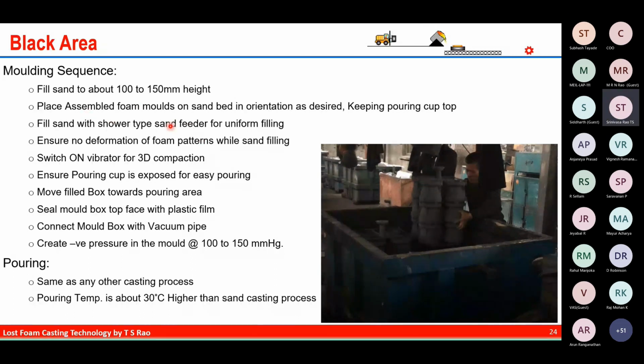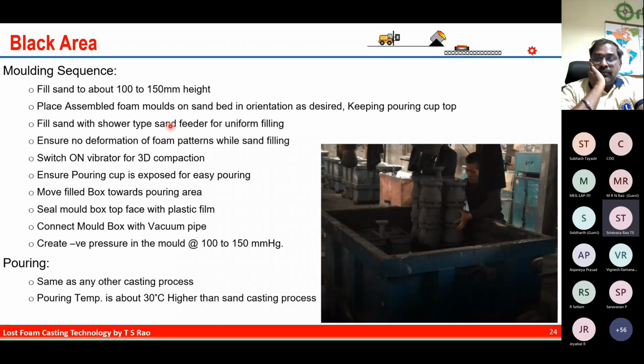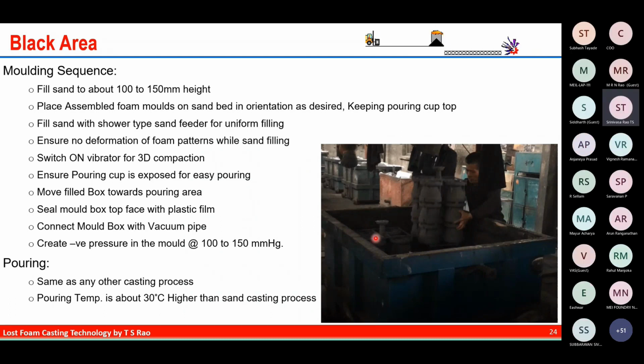And once the assembled foams are kept on the bed in any orientation, not necessarily we need to keep upside right. It can be 45 degrees. It can be in any orientation, depends on the sequential filling. Fill the sand with the shower type sand feeders for uniform filling of the mold. Ensure no deformation of the foam patterns while sand filling. Normally, when the sand is being poured into the mold box with velocity, the foams are likely to get disturbed. The position is likely to get deformed. That is, in some foundries I have seen they use some reinforcement to ensure that the foams are not shaking while sand filling. And next, while filling the sand, the vibration is switched on for the 3D compaction so that the sand get packed into the mold firmly.